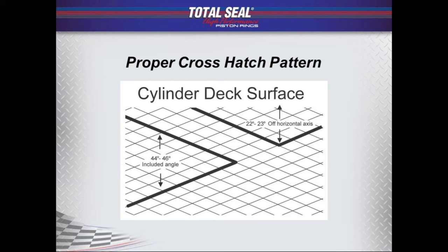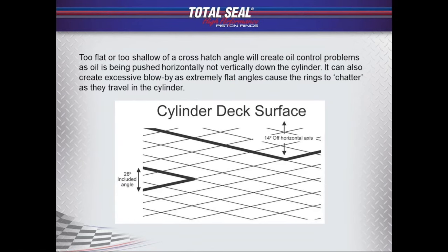The flatter the crosshatch angle, the slower the ring rotation speeds. And this illustrates that. You can do a real flat crosshatch angle, and this one's not that flat. This is 28 degrees included or 14 off the deck. As we flatten the crosshatch angle out, you start to slow ring rotation speeds. But it also acts kind of like a dam. The flatter the crosshatch angle, typically the lower the blow-by numbers. The more vertical the crosshatch angle, typically the higher the blow-by numbers, an easier travel path up and down the bore.